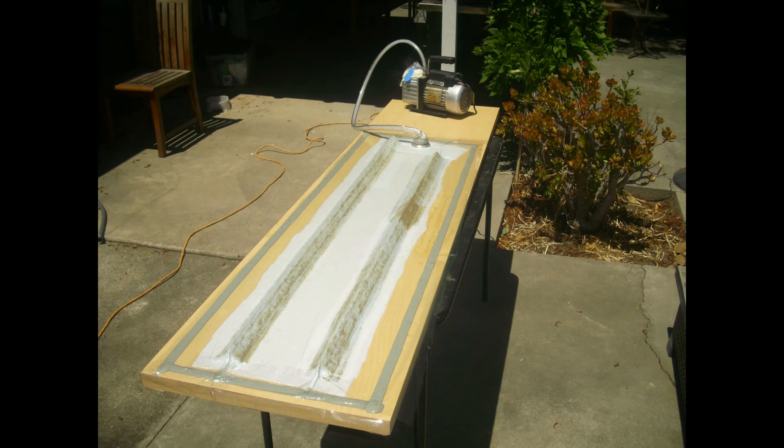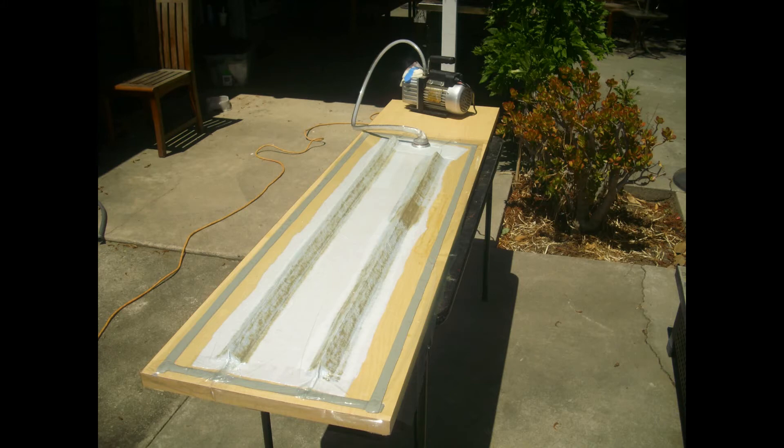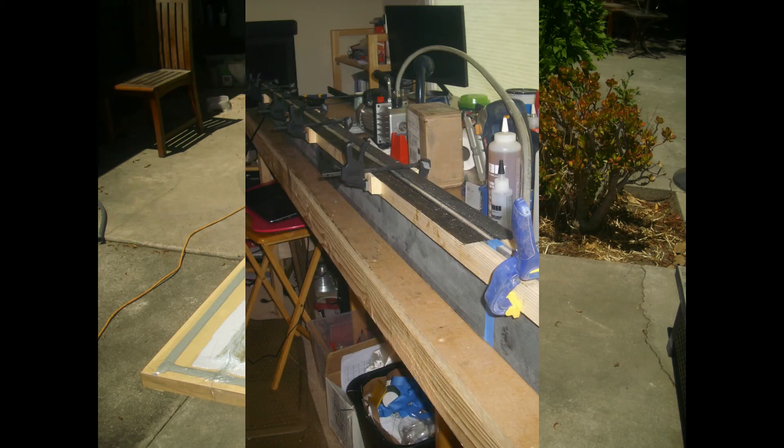This photo shows how I produced the shear web flanges. I used standard aluminum angle brackets placed on a section of plastic countertop material. The carbon fiber fabric is wider than the angle brackets, and the excess is trimmed off post-cure before the part is removed from the mold. I used narrow 3-inch wide woven edge carbon fiber fabric so I didn't have to cut long strips and the edges don't fray during the wet-out process. Also, it's important to use peel ply on both sides of this layup so that it has the proper surfaces for bonding on additional parts later in the assembly process.